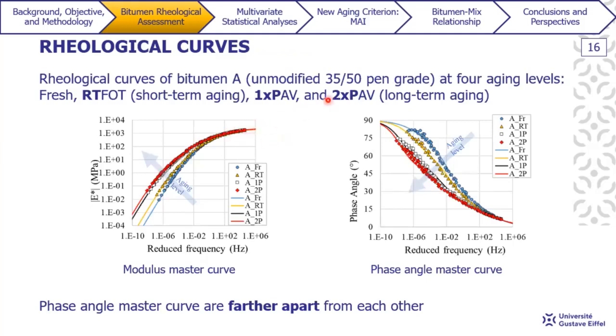So now here we have some results of bitumen A that was RTFOT aged and 1 and 2 times PAV aged in the laboratory. For the modulus master curve, I'm just going to explain this figure. The blue curve represents the unaged bitumen. The yellow one is the RTFOT aged. The black one is 1 PAV aged, and the red one is 2 PAV aged. I'm going to use the same color to represent the same aging condition.